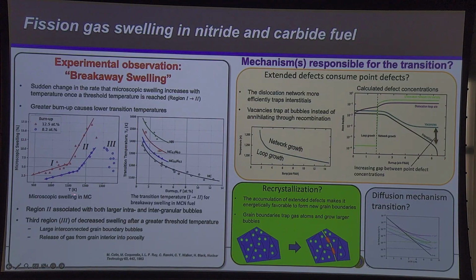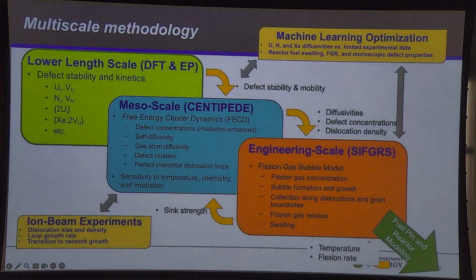This is swelling versus temperature, similar things as burn-up. If you go above a certain temperature, the slope of this line, which means the swelling rate, goes up a lot, and that's not great. So we want to understand how that inflection point depends on temperature, irradiation conditions, and so on. This is the same kind of concept that I've already described several times, starting with low scales, defining parameters, identifying the relevant physics, coupling all of that in a large-scale model, connecting to experiment where it makes sense, using machine learning to optimize this, and then saying something about performance.